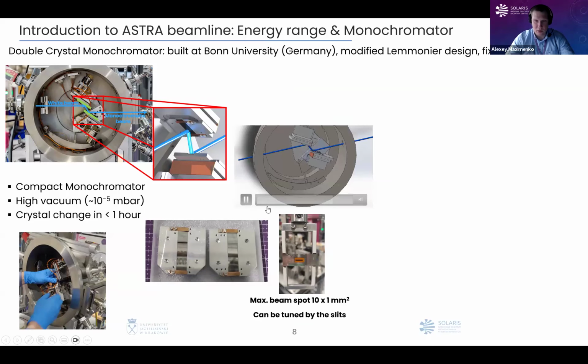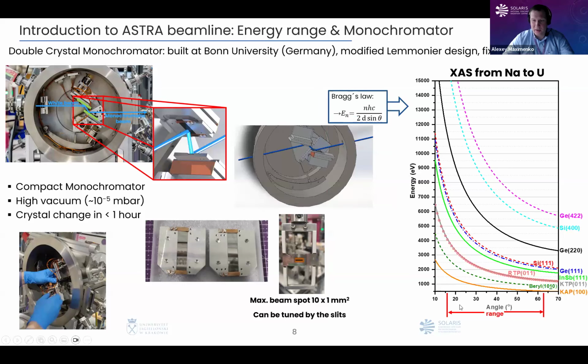Why is it so important for us? Because as you can see, the angle range in which our monochromator works is between 15 and 62 degrees. And in order to achieve the energy range which we claim, we need to change the crystals in our monochromator. Definitely there is a solution to make it motorized, but then the cost of such a monochromator would be very high. In our case, we actually use our hands to change these crystals.